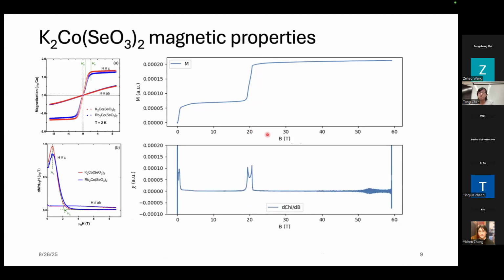The interesting thing we found in this measurement is that the transition actually has two peaks. This double peak structure might be indicating some extra phase in between, which is consistent with the numerical calculations that there exists a high field supersolid phase here.